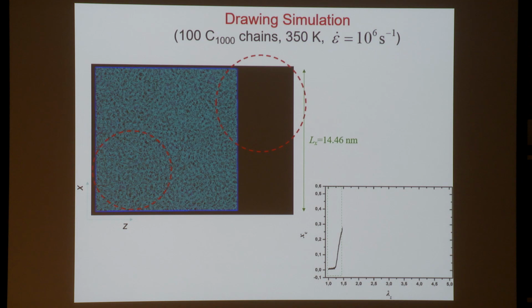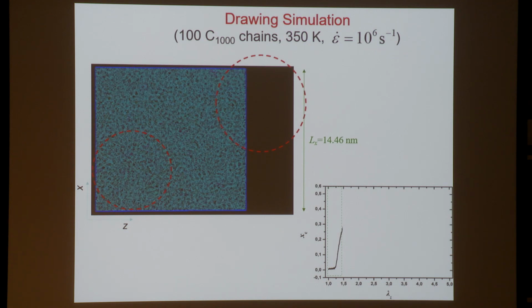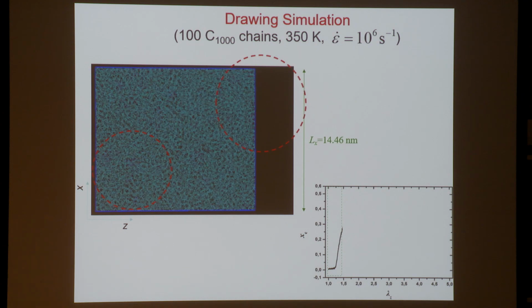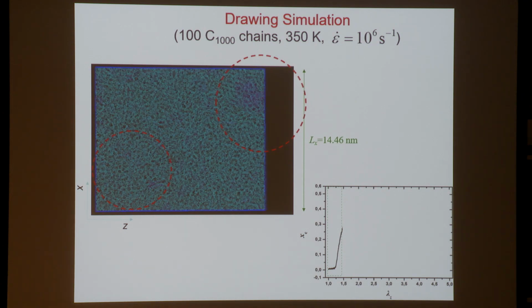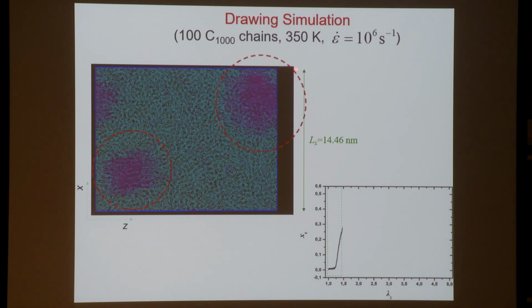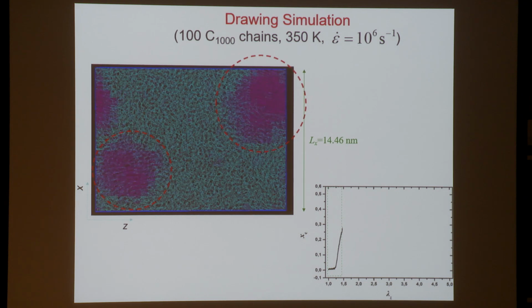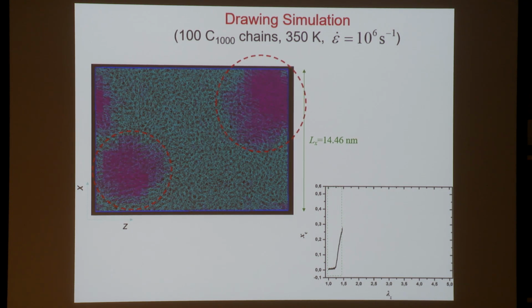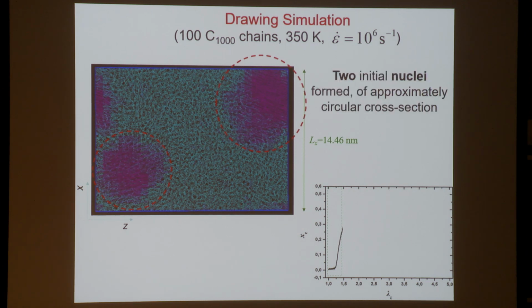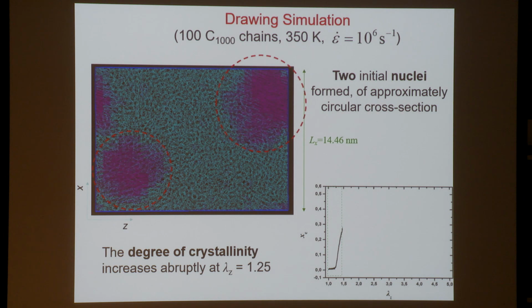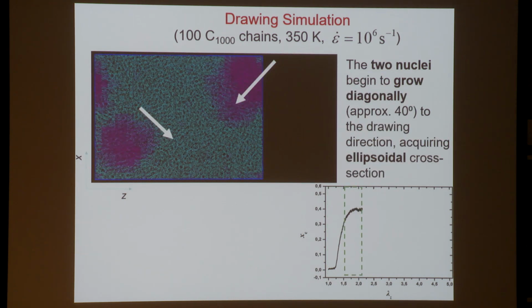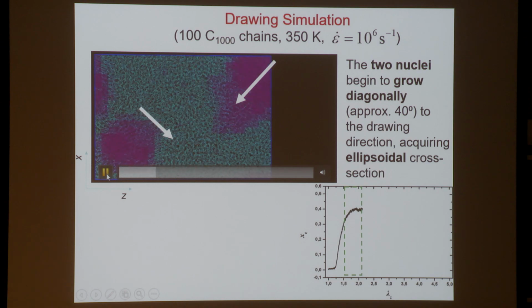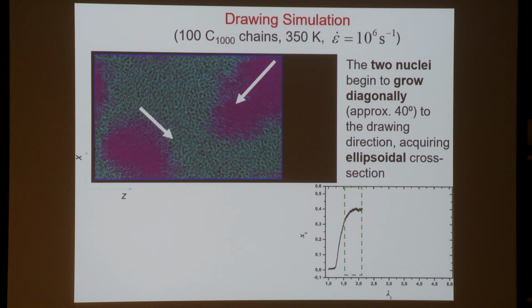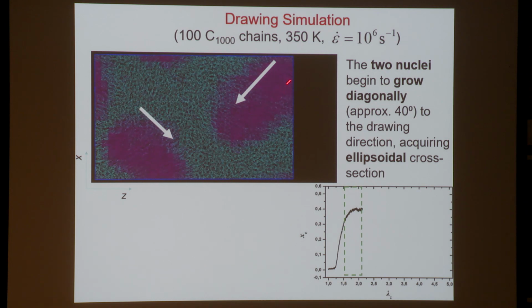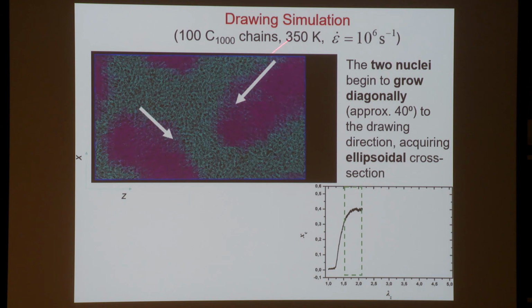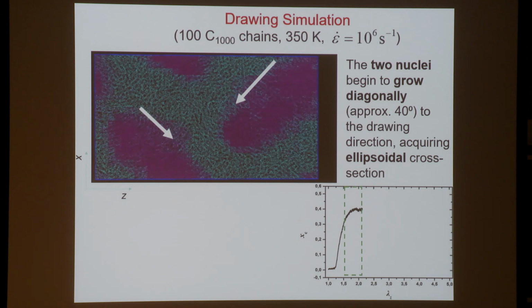Now let's look at a movie of a larger system, 100 C1000 chains, subjected to a lower deformation rate, 10 to the 6th inverse seconds. We see that we have the emergence of 2 nuclei here, which are of roughly a circular projection, and the degree of crystallinity really starts rising at a stretch ratio of roughly 1.25. If we continue with this crystallization, we see that these crystalline regions grow, and they grow in a rather anisotropic manner. They become more elongated, such that the projection is more elliptical than circular.